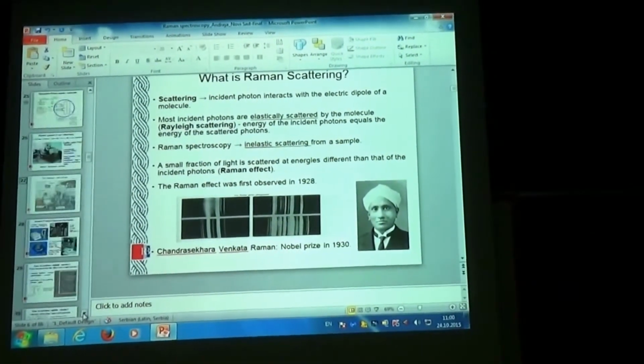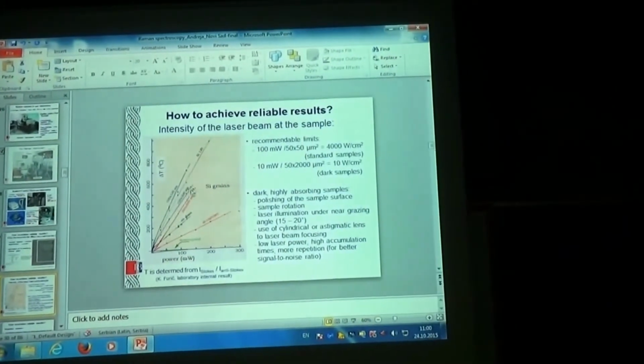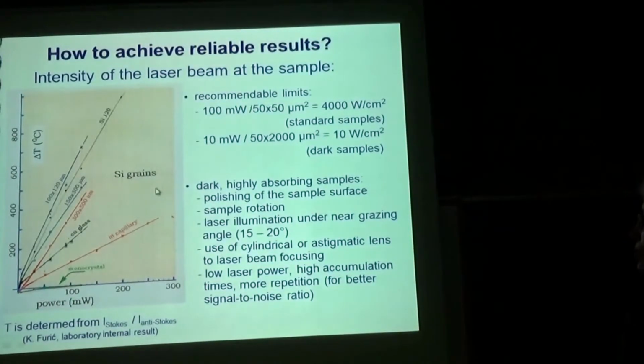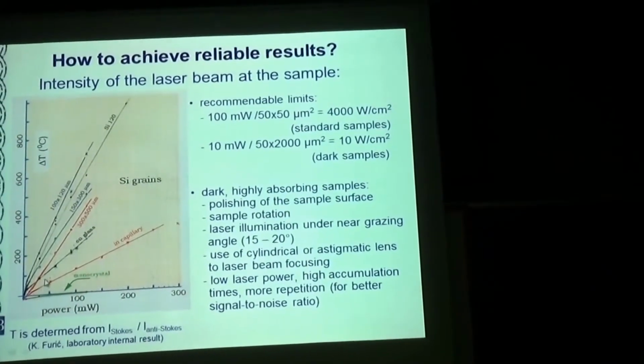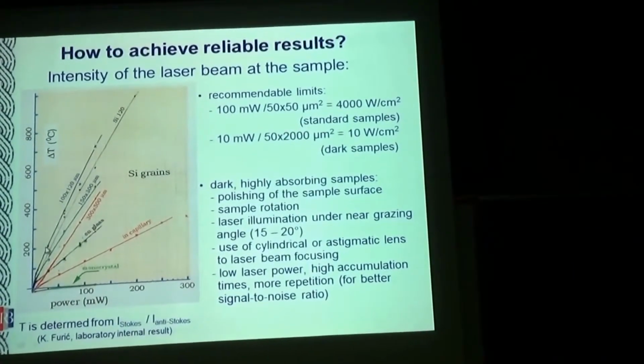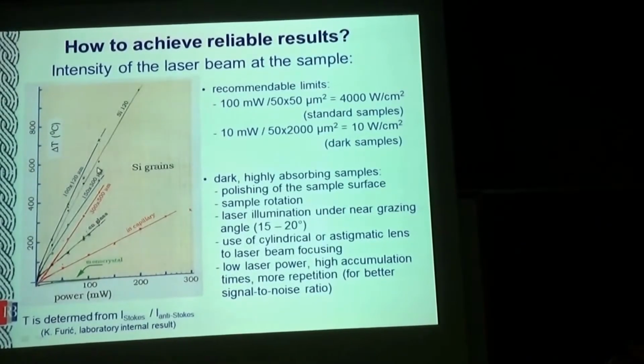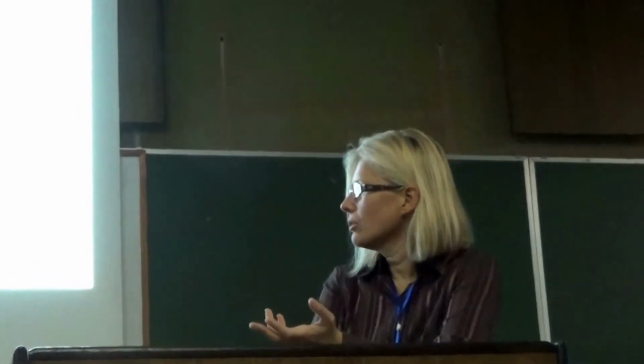So it always depends on the sample. If you have a very light, white sample, then heating is not so strong. I didn't specify heating temperature because it depends on the sample. With silicon - this is an example my old boss did - he used silicon grains because they are dark. Using only 20 milliwatts, he already got 200 degrees centigrade, so the heating was huge. But if you work with zirconium oxide or titanium oxide, they are white and heating is not so large. You can always record the Stokes and anti-Stokes parts of the spectrum and calculate your temperature.